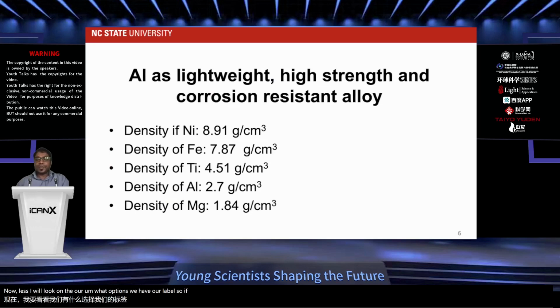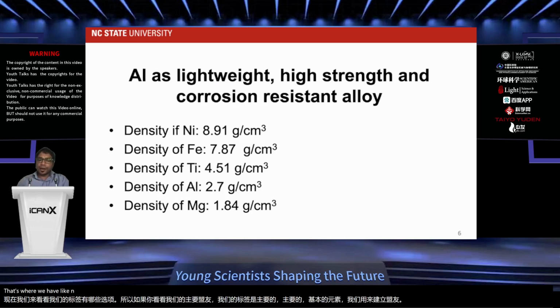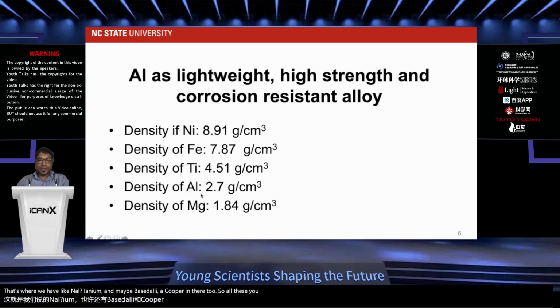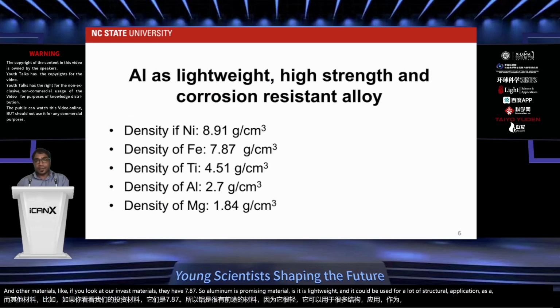If you look at the main alloys we have available, the principal elements we use to make alloys are nickel, iron, titanium, aluminum, and magnesium based alloys. Copper is in there too. You see that aluminum is 2.7 gram per centimeter cube, while iron-based materials have 7.87. So aluminum is a promising material. It is lightweight, and it could be used for a lot of structural applications as a light material.